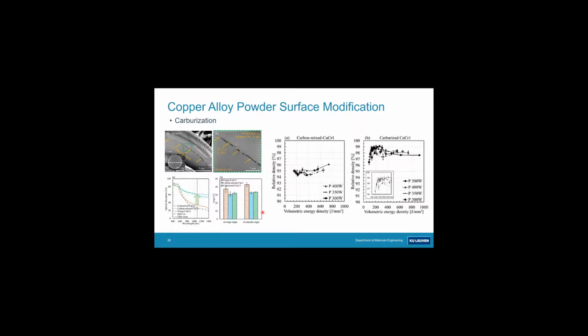So during this carburization heat treatment, you basically diffuse out chromium, which binds to the carbon which you decorated the powder with, and you form carbides. And these carbides, they are again well wetted by liquid copper, so they were very effectively incorporated in the melt.